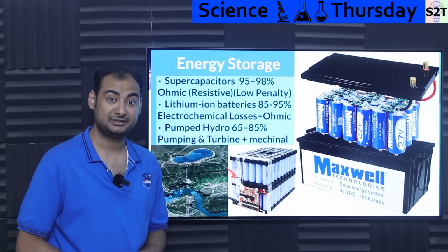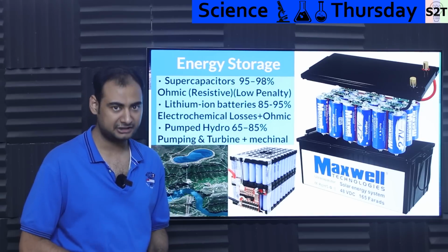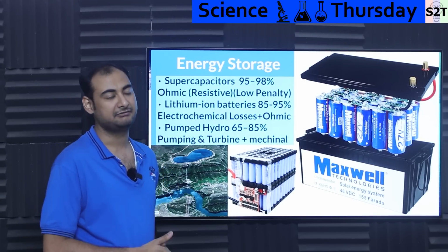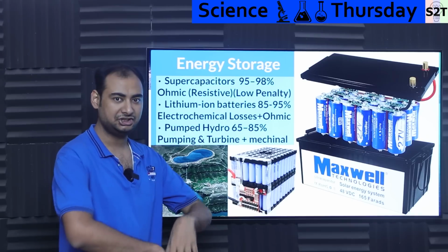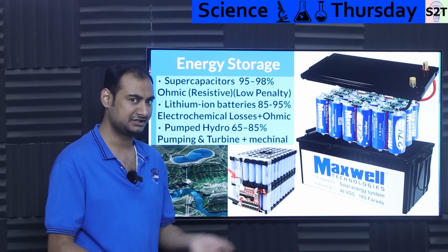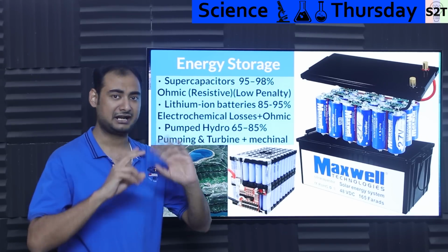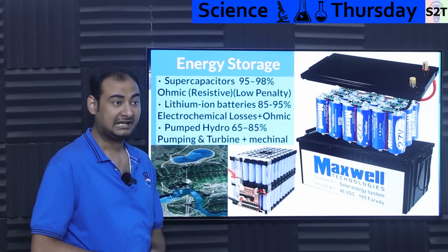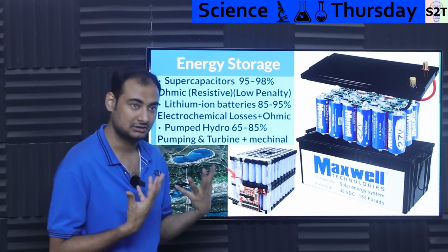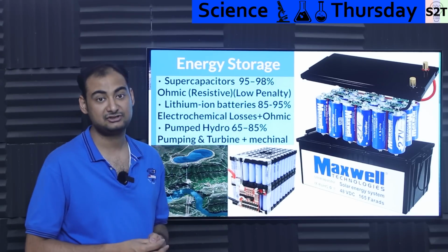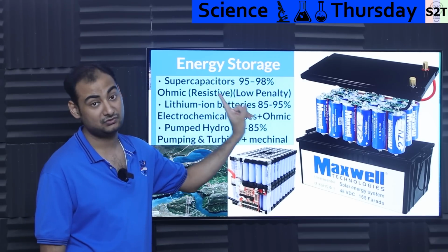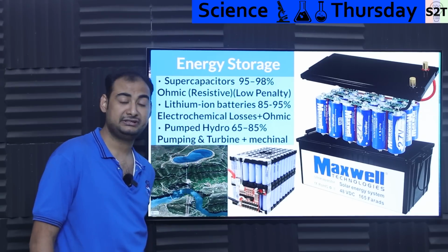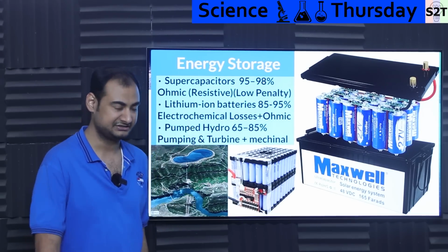Now, what about lithium-ion batteries? Well, again, they are a significant upgrade from lead-acid batteries. But when they started, in the 1990s, you had the era of the lithium-ion patent, and Sony starting to bring out lithium batteries for their Handycams. That was 85%. As we became better, more efficient, more adept at manufacturing and cell geometry, we pushed that puppy to 95%. So if you have money, you're going to get 90%. If you have a lot of money, you're going to get 95% right now.